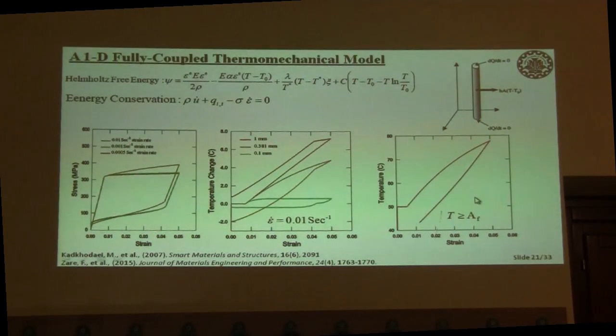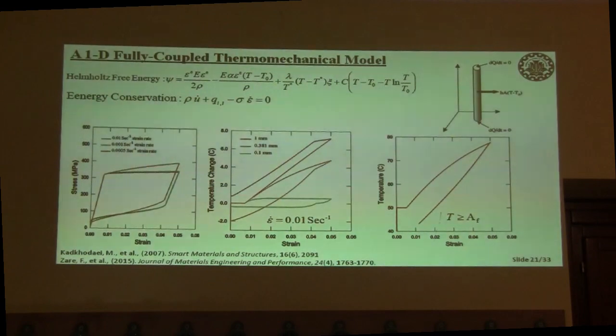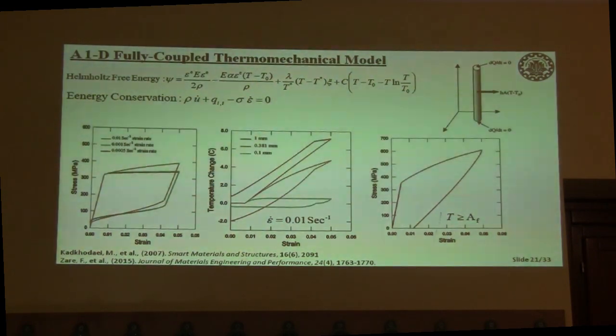Another side effect is that maybe I can begin loading on a shape memory alloy whose temperature is initially more than AF—it's initially austenitic. But after unloading, the temperature is below AF, it's no longer austenitic. You can see that although temperature is more than AF, I would see some residual strain.